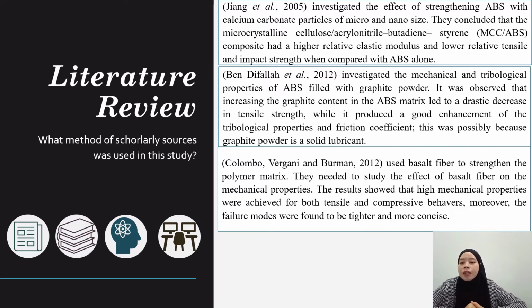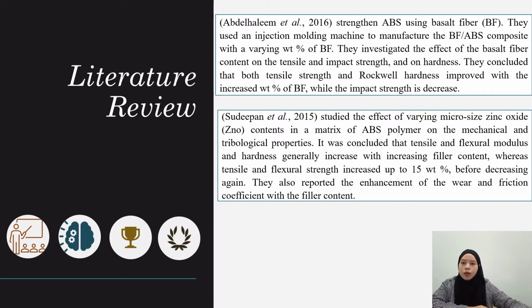Moreover, the failure modes were found to be tighter and more concise. Next, according to Abdelhaleem et al., 2016, they investigated the strength of ABS using basalt fiber. They used an injection molding machine to manufacture the basalt fiber and ABS composite with varying percentages of filler. They concluded that both tensile strength and Rockwell hardness improve with the increase of percent basalt fiber, while the impact strength decreases.